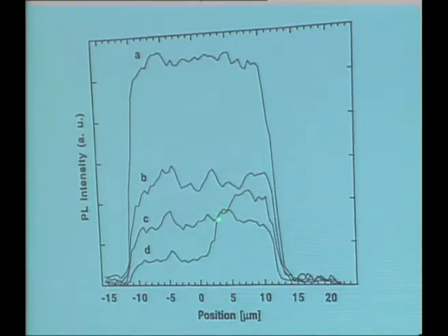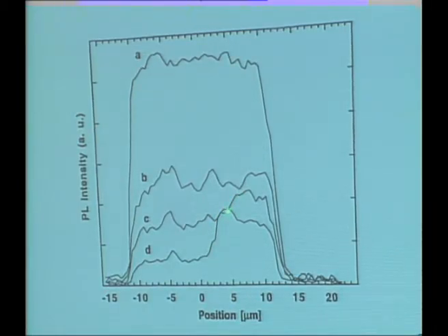Maybe that's because these conducting P and N regions are so close by. I don't know. This is not a good thing, okay? Because it tells us that the photoluminescence here is already down by a factor of 5 from the pure material. And remember our discussions of yesterday or the day before, the photoluminescence is the maximum quantum efficiency, the maximum you could ever expect for the electroluminescence. Okay. So this is a lovely device, many, many advantages. Okay. This I don't like. Maybe it can be fixed, but you see the point.